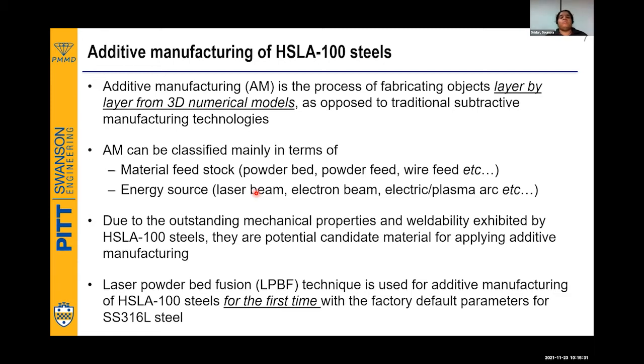But the problem with electron beam is that your bed temperature, the powder bed temperature, is pretty high, due to which certain materials will have difficulties. But since it is kind of a preheating, the cracking is typically low in electron beam. And the third one is the electric or plasma arc. Typically this electric or plasma arc is used for wire feeding. It actually means all the old welding machines are being converted to new additive manufacturing machines, as simple as that.